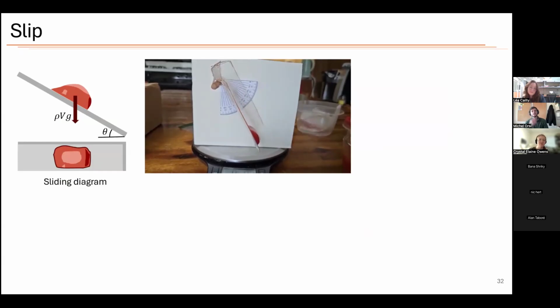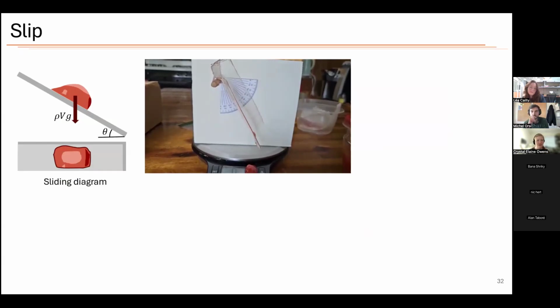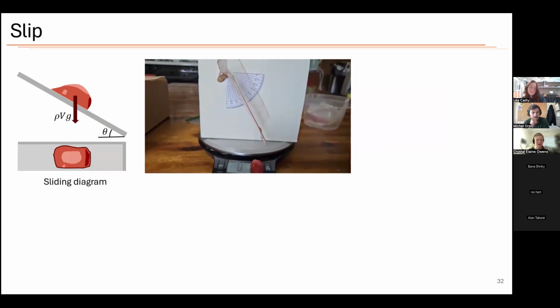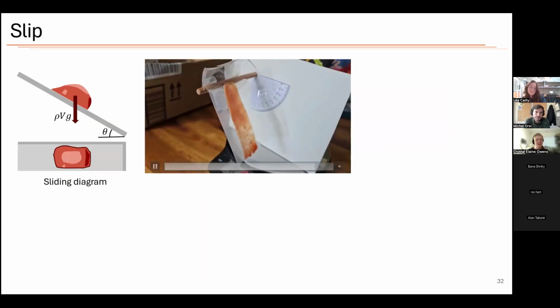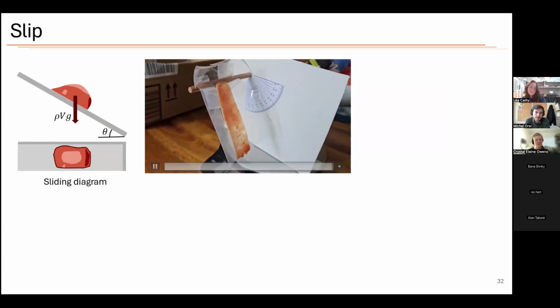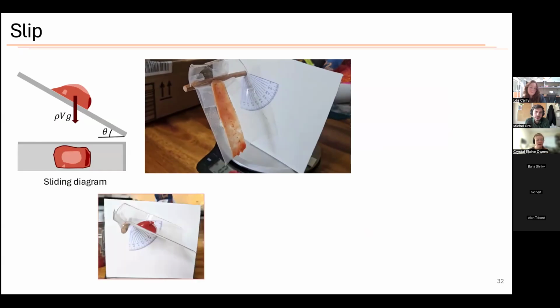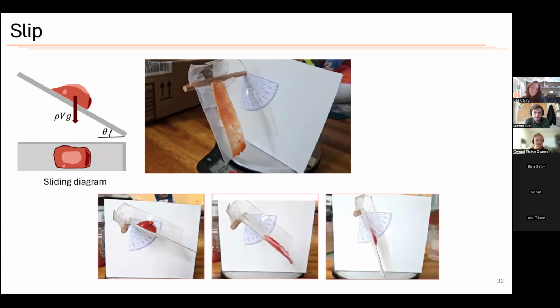And so you add ketchup, you watch it slide down, and then you can measure the sliding velocity, which is the key parameter, as a function of the mass and the angle, which describe the stress that's going to be applied. We did this, and in this particular case, it leaves a large track of fluid as it goes down. So this is more like case B that we were looking at before. We did this for several different cases with different amounts of fluid and different measurement angles.